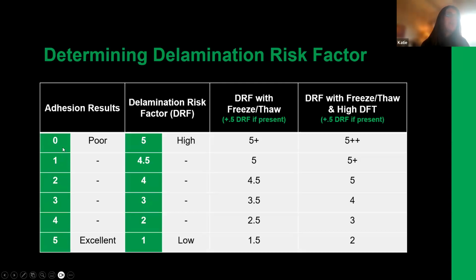If we have very poor adhesion, we're going to have very high risk. If we have very good adhesion of the existing system, we're going to have very low delamination risk factor. So that's pretty simple. If you have poor adhesion, your delamination risk is high. If you have good adhesion, your delamination risk is much lower.